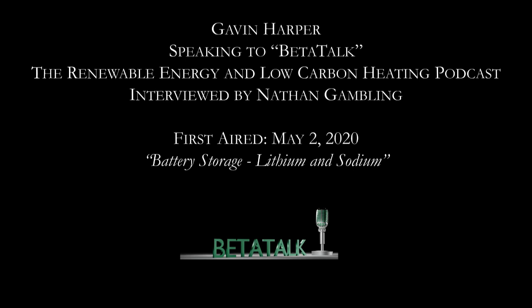cathode. The sodium's slightly larger, and the theoretical energy density is not necessarily as high compared to lithium. So that's one advantage of lithium in transport. But when you're looking at fixed storage applications, the energy density is much less important, because it's just a box sat there. The cost, the sustainability and the lifetime are much more important than a slight increase in mass. That's the reason to move to sodium.